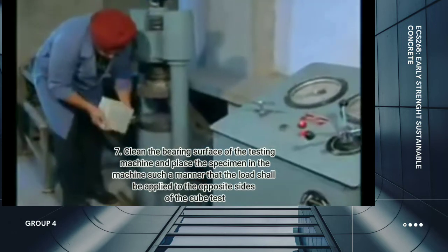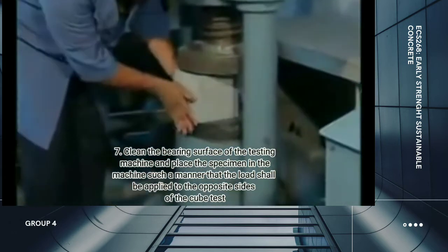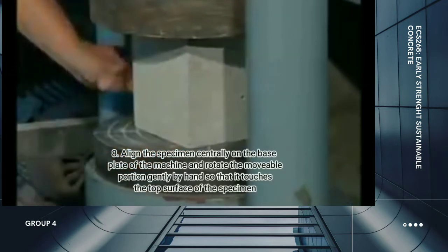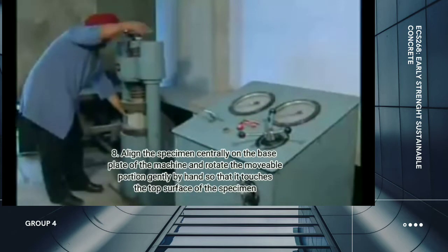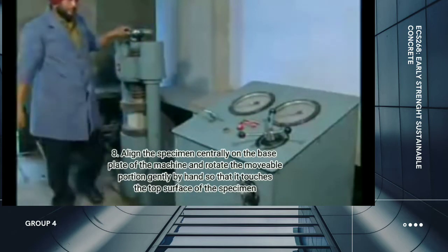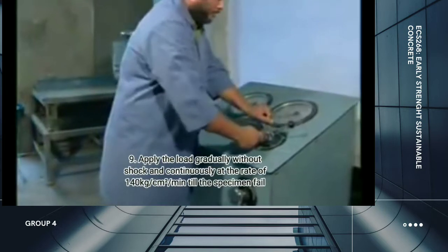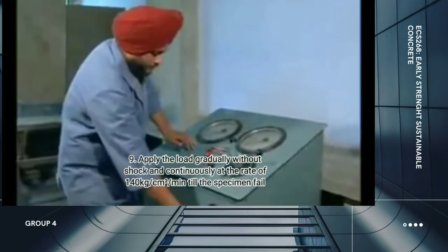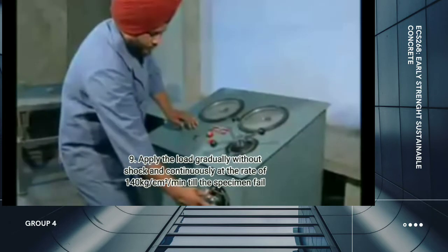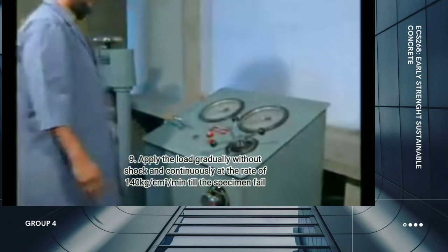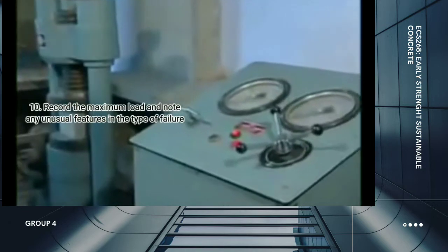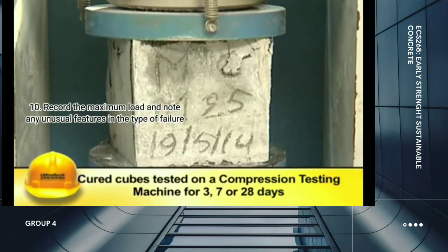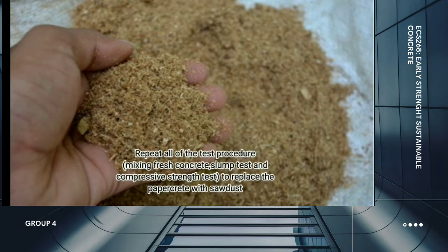Place the specimen in the machine in such a manner that the load shall be applied to the opposite sides of the cube cast. Align the specimen centrally on the base plate of the machine. Rotate the movable portion gently by hand so that it touches the top surface of the specimen. Apply the load gradually without shock and continuously at the rate of 140 kg per square centimeter per minute until the specimen fails. Record the maximum load and note any unusual feature in the type of failure. Repeat all of the test procedure, replacing the papercrete with the sawdust, and record all of the data in the table.